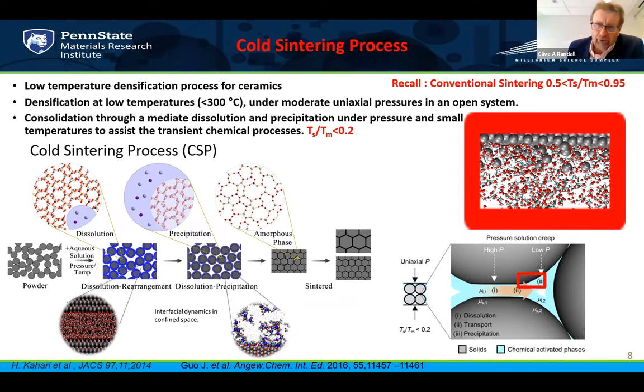And you can push those temperatures down with sintering aids and so forth. But typically it's all high temperature. In the case of oxides, this means we're typically sintering from 1,000 degrees to 1,500 degrees. And as many of you know, even changing from 1,200 to 1,300 can make big differences to the expenses and costs of your furnacing and kilns and the lifetime of those kilns.